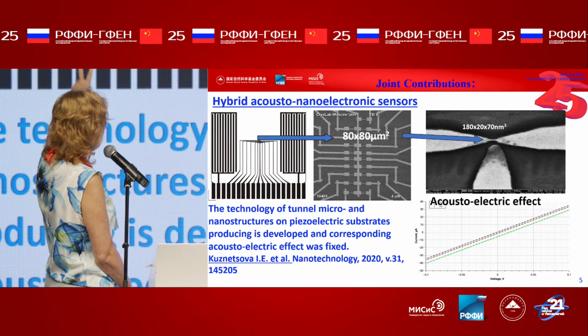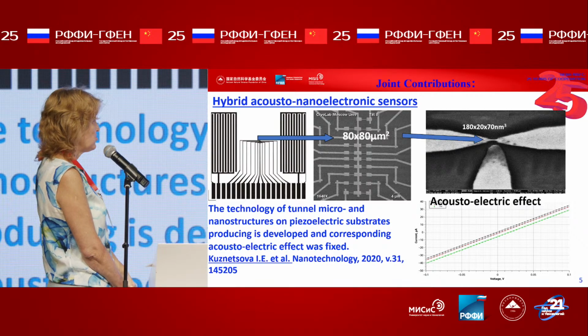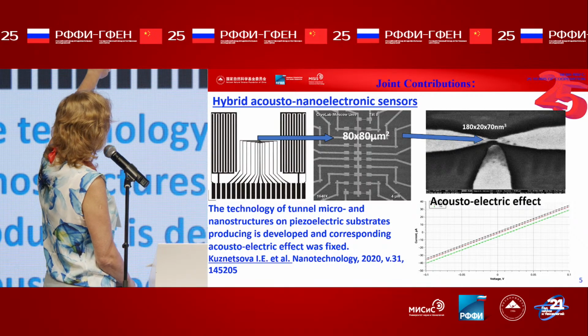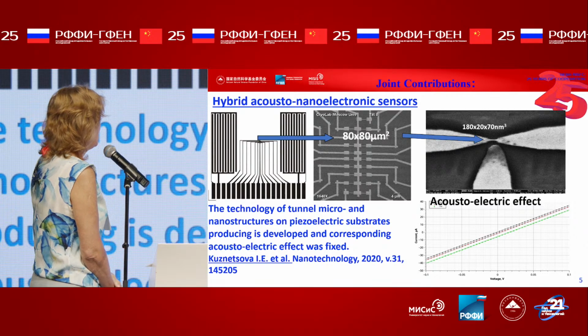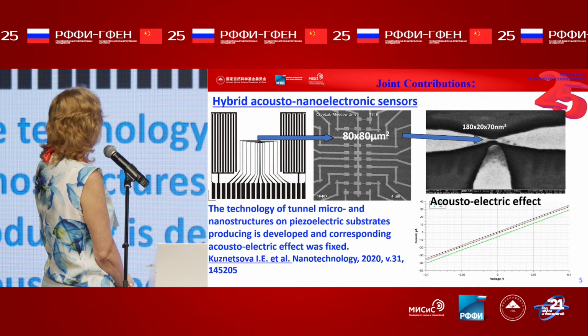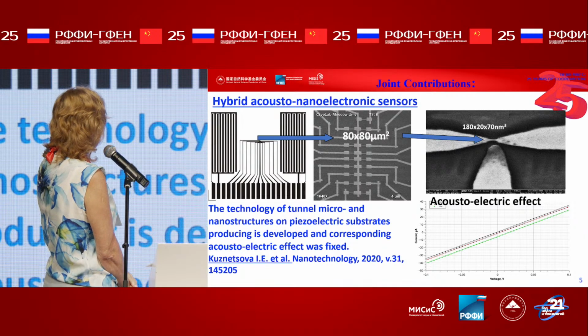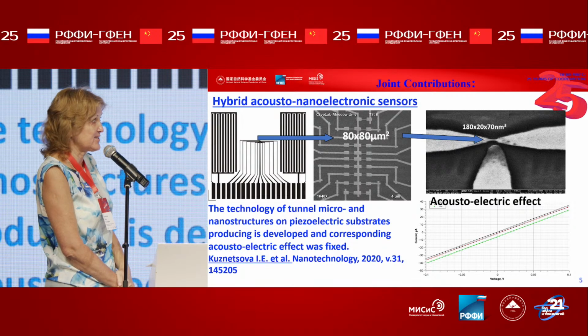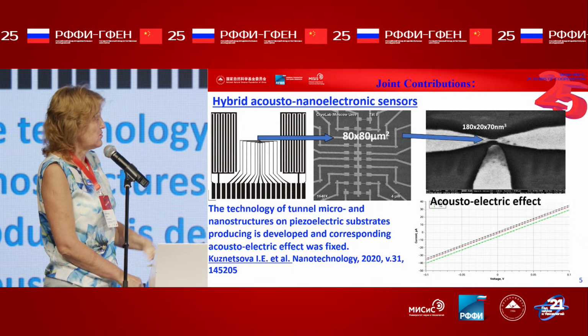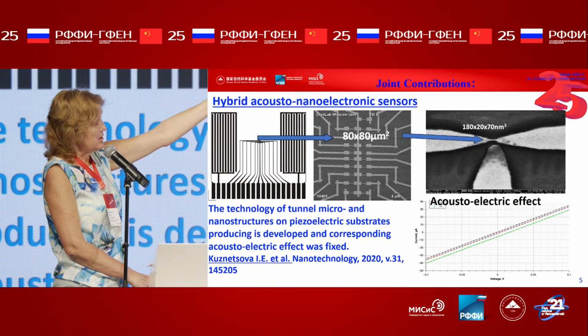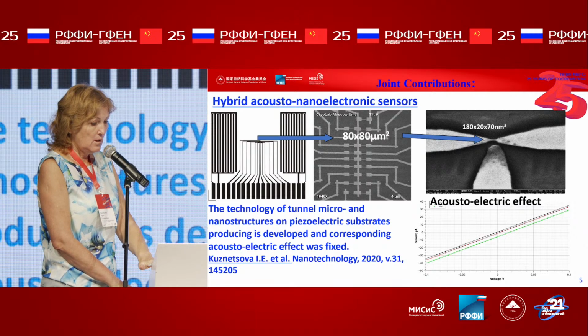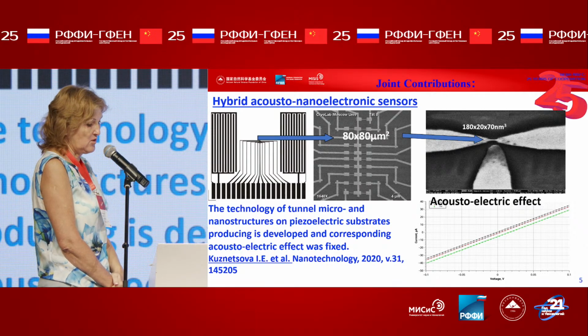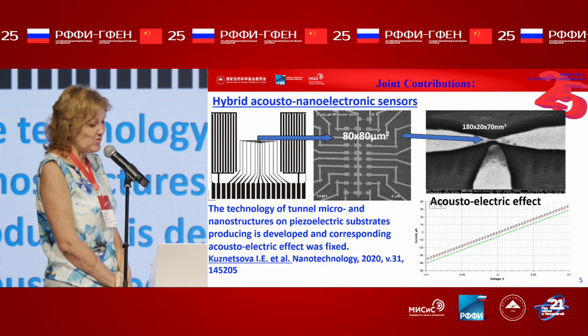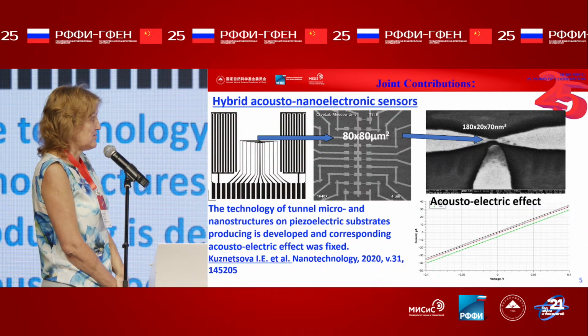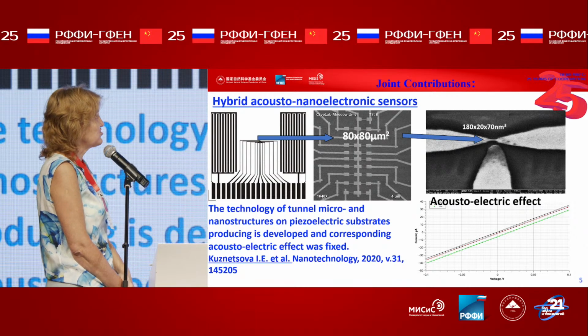First time, we placed two interdigital transducers which allowed to excite acoustic wave propagating in piezoelectric plate, and we placed between them nanoelectronic structure, and we developed the technology of producing of tunnel micro and nanostructure on piezoelectric substrate. This is not simple task. You see we have possibility to obtain nanowire, and by measuring current voltage characteristic of such nanowire in presence of acoustic wave in piezoelectric plate, we watch acousto-electric effect, you can see. And this is one step to develop the new hybrid acousto-nanoelectronic sensor. Next slide, please.